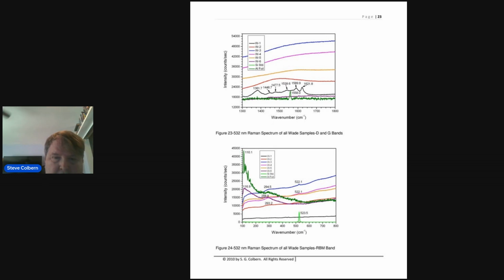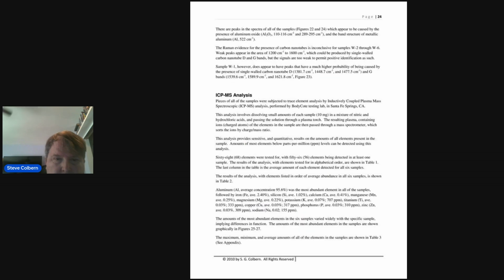Next page. Okay, now we're down to the ICP-MS analysis. We tested for 68 elements. You can't test for every element with ICP-MS; iodine, sulfur, and volatile elements are not able to be tested for. We detected 56 elements in at least one sample. I think that was sample W6, as I recall.